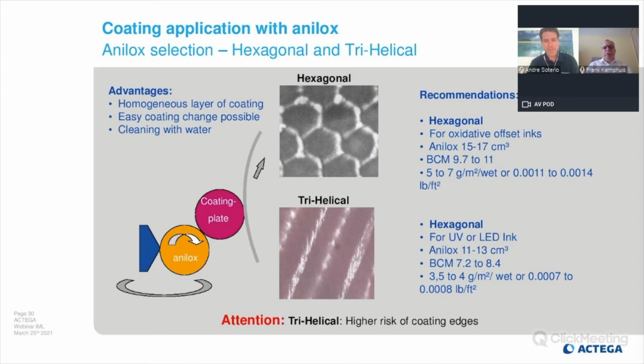For IML, we recommend the hexagonal roller, and if you're using offset oxidative drying inks, then we recommend 9.7 to 11 BCM to apply the right amount of coating. If you are using UV ink or LED ink, you can reduce a little bit the amount of coating, and you can use a 7.2 to 8.4 BCM roller. Why we recommend the hexagonal roller? Because with tri-helical, we saw in practice that you have a higher risk of coating edge build-up when you apply the coating.